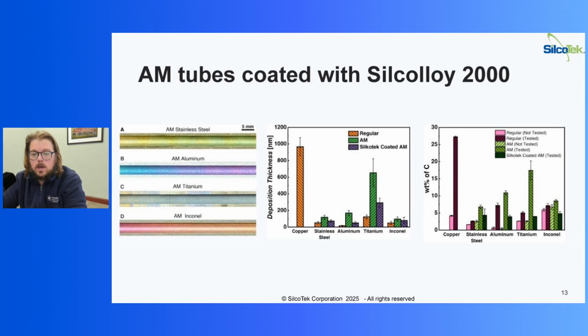And then finally, you can see how it didn't quite get it down to the same level of carbon buildup on all of them. But if you'll notice for aluminum, as well as for Inconel and titanium, the additively manufactured tube with the coating on it actually produced less carbon than the standard tube itself. And I'd be really interested to see what these would look like if the standard tubes were coated with SilcoTek. I believe they may have done that. I'll have to look a little bit harder. However, this was a really nice paper showing just how beneficial having inert surfaces, especially to stop catalytic breakdown like the jet fuel touching these tube walls, can do for you and for a variety of other applications.